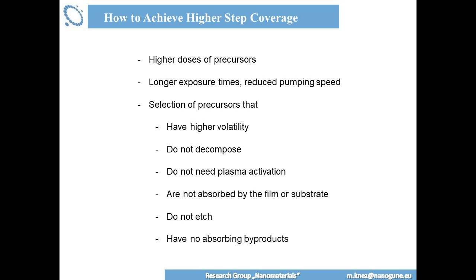You need to have precursors that have a high volatility. Well, this is valid for all ALD precursors. They should not decompose. They should ideally not need plasma activation because of what I mentioned before. You have a higher recombination rate. That means the lifetime of those plasma-based reactive precursors is very short compared to others. They should not be absorbed by the film or the substrate. What I just said before, water should not be soaked into the substrate, or oxygen.